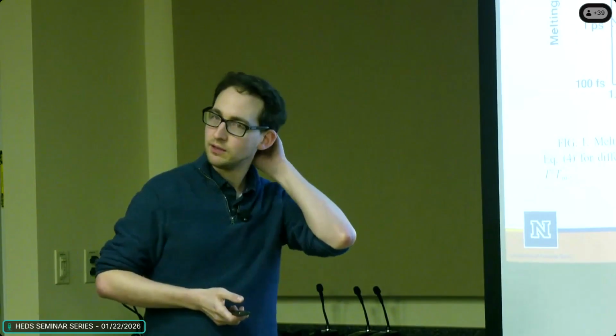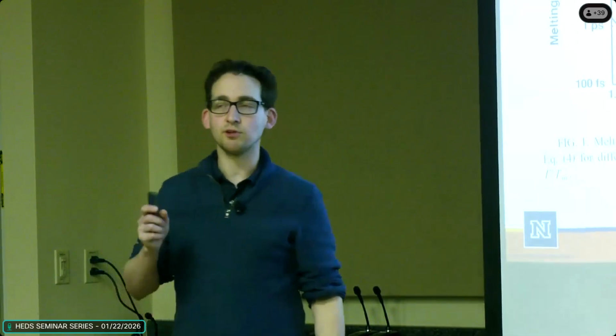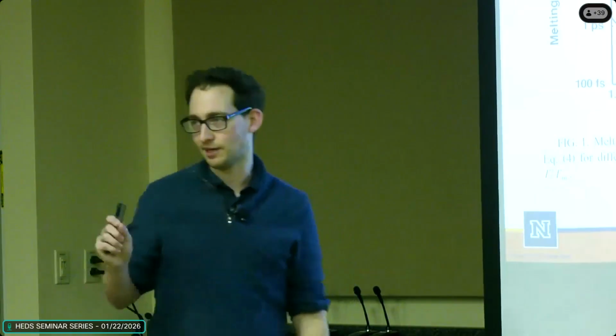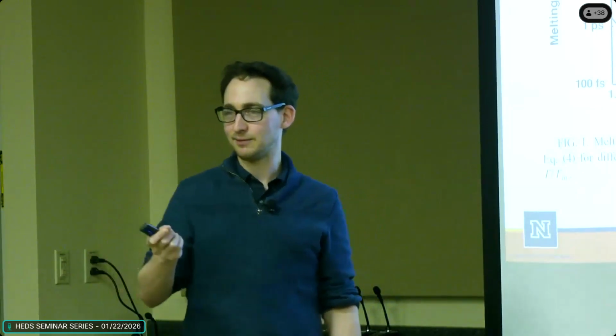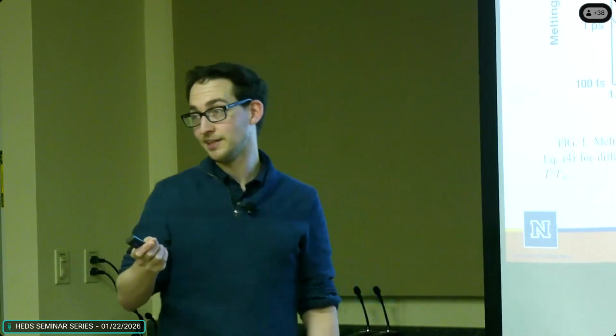Yeah. Is it possible to try to do an MD simulation of something like this to see a movie of it? We've tried to do MD simulations. The problem with the MD simulation is this bond hardening effect. If you want to do a classical MD simulation, the question becomes which potential do you use? And if you have a system where the bond strength changes in time as a function of electron temperature, that becomes a very hard classical MD simulation to do. So then you do quantum MD, maybe you can do quantum MD, but that is beyond my abilities to do at that point, yeah.